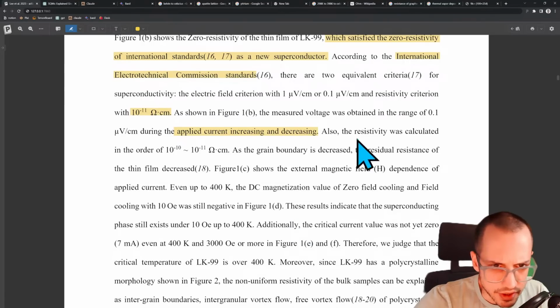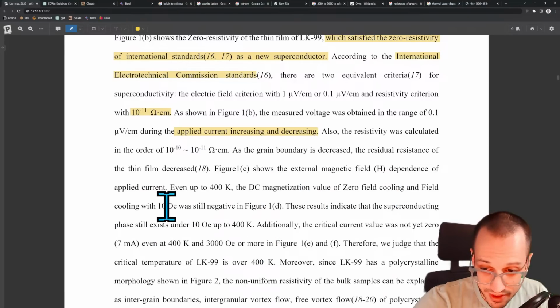Okay, let's get back to it. The external magnetic field dependence of applied current, even up to 400 K, the DC magnetization value of zero field cooling and field cooling with 10 Oe was still negative in figure 1. This result indicates that the superconducting phase still exists under 10 Oe up to 400 K.